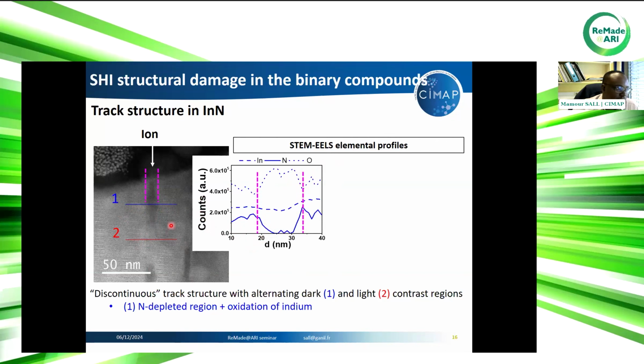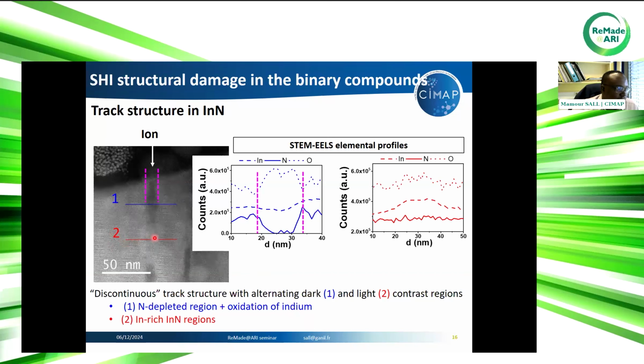So in region 1, we have nitrogen depletion of indium nitride, and the remaining indium is oxidized by air when we put the sample in air after irradiation. We did the same analysis in region 2, so in the light contrasted region here. So here we follow the red line. What we can see here is that the nitrogen content is almost constant, and we have an increase of indium inside the track here. So region 2 is, let's say, an indium-rich indium nitride region. So in the volume of indium nitride, we have this alternating region of nitrogen depleted region with oxidized indium, and also indium-rich indium nitride region.